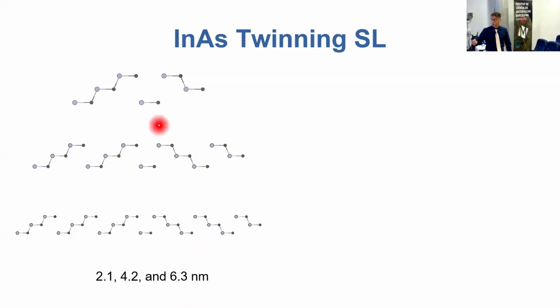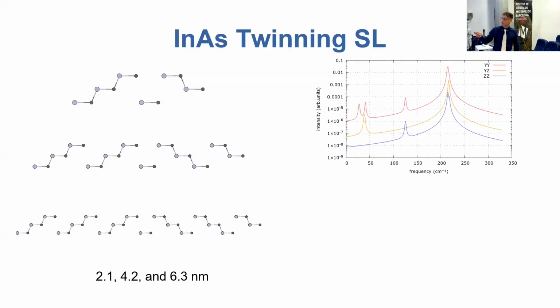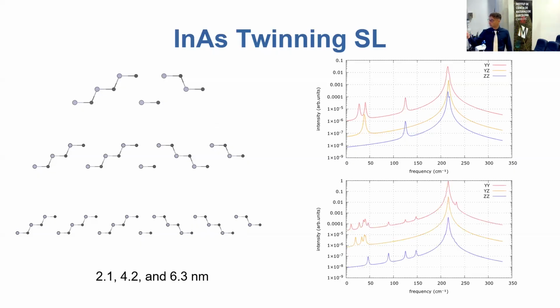These computations are particularly heavy. And we computed the Raman spectra of these 3 superlattices. Here I show you the Raman spectra of the shortest one and of the longest one. And you can appreciate how, even in this case, the imposition of a superlattice structure still works and affects the Raman spectra of the material.